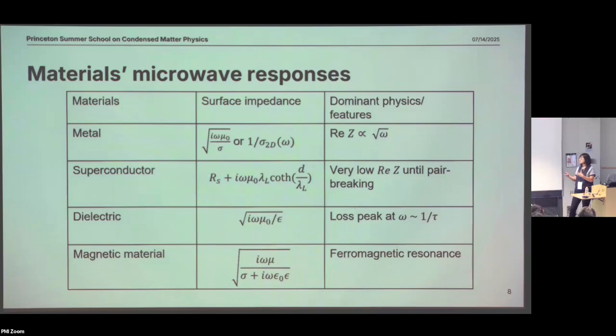Loss channel could be coming from the type 2 vortices, or it can be coming from just pair breaking, or your temperature is too high, larger than Tc or something. And then it has this imaginary part. This imaginary part is inductance. It's the kinetic inductance of the Cooper pairs. And then, as you can see, it has to do with the D. D is the thickness of the superconducting film. So that's to say, when the D becomes very thin, so D is very small, then this term becomes very large. So in 2D superconductors, the kinetic inductance term really dominates. It has a lot of weight.